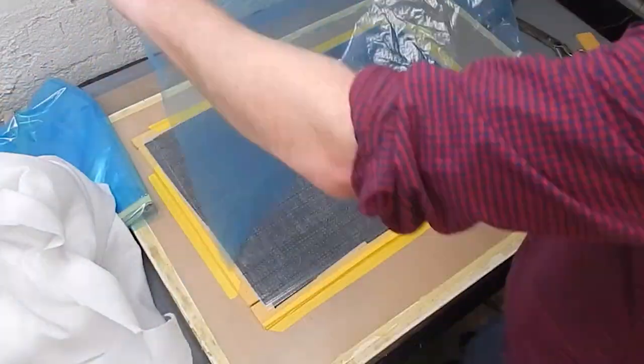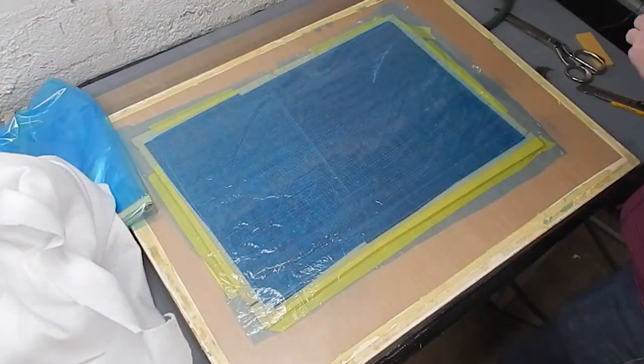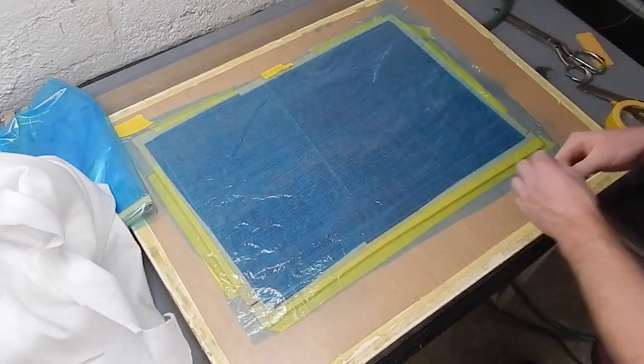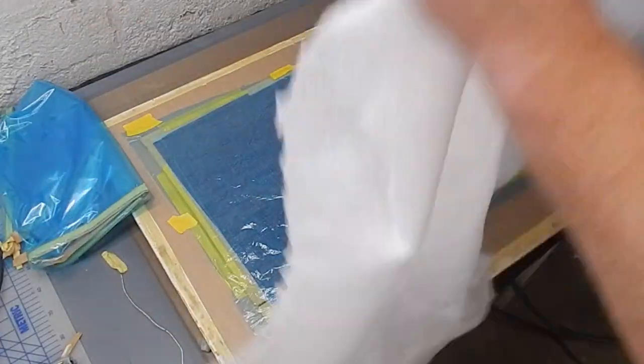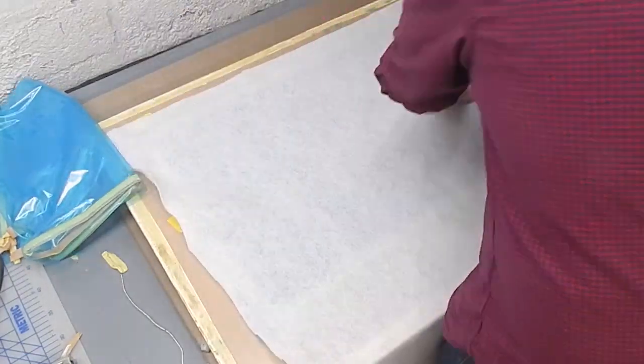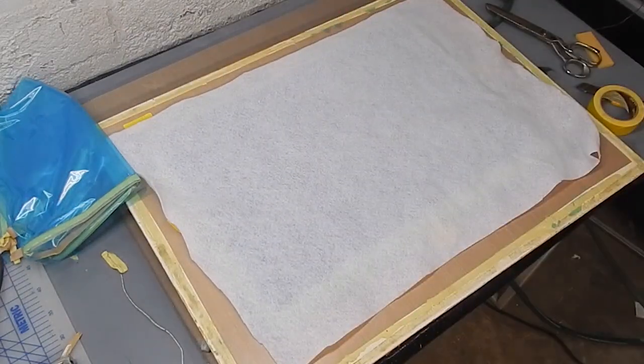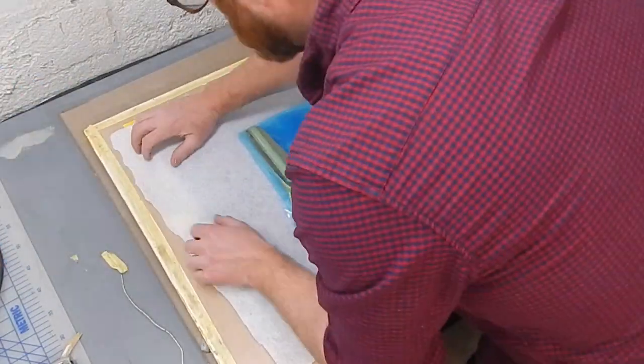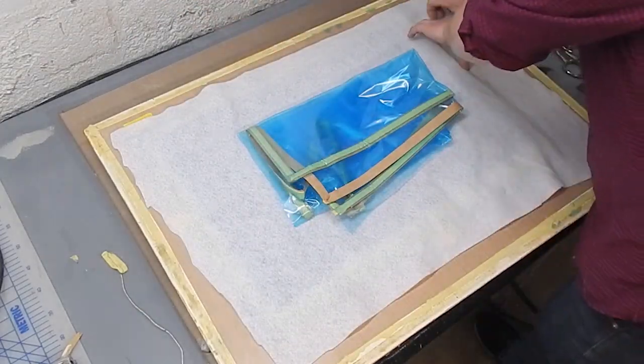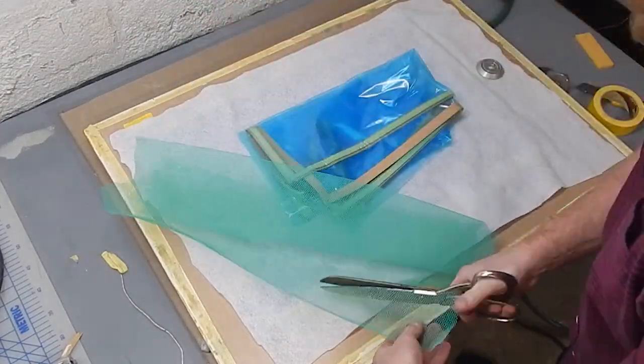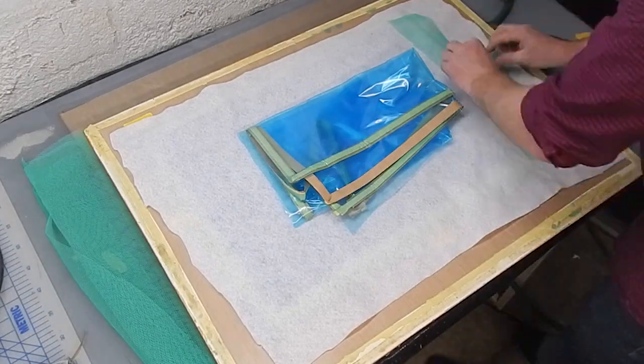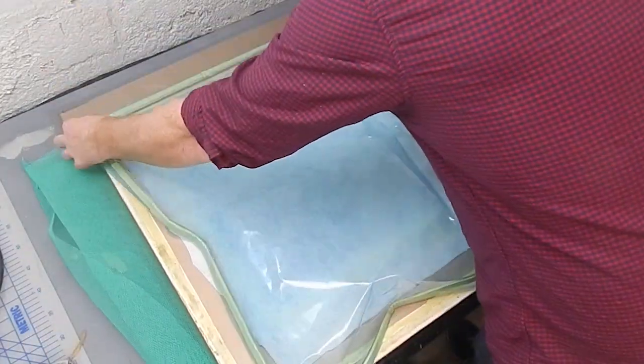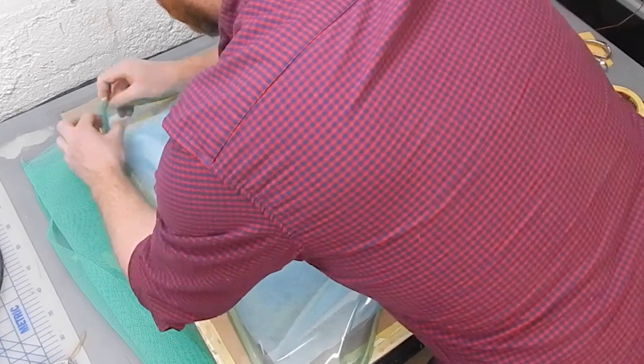And some nice perf release film. This is the fancy stuff. It's flexible. I think this is P3 perforation. And then just a little bit of breather, four ounce light breather over everything. Trying not to bleed too much. And just underneath the vacuum, a little bit of manifold made out of green infusion flow mesh.